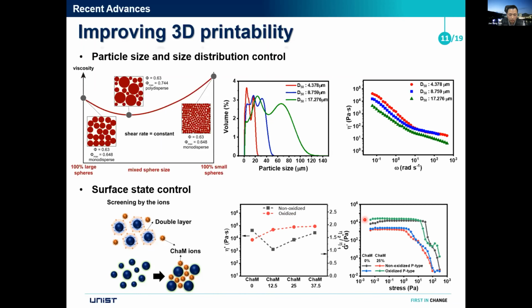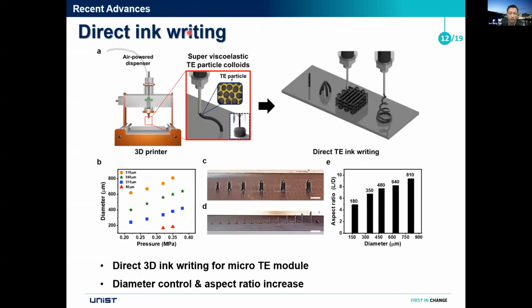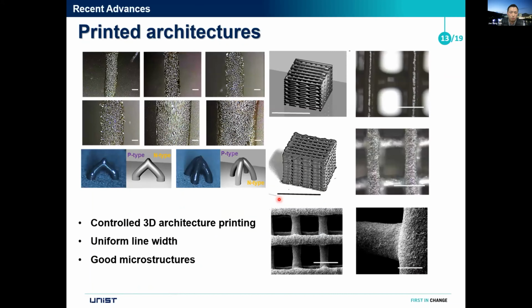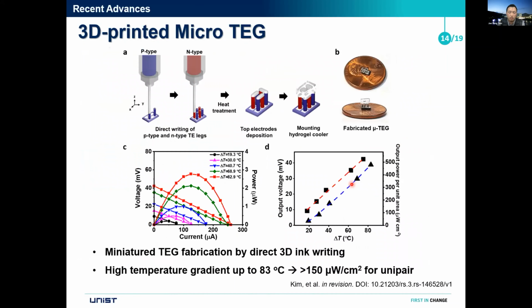By using these inks, we realized direct ink writing, or 3D ink writing, to produce thermoelectric filaments. The diameter of these filaments ranges from 100 micrometers to millimeter scale. And then we can design and fabricate some complicated architectures, P-type, N-type bridge structures, and some scaffold-like structures. And these thermoelectric layers have quite high ZT values, about 1.1 for P-type and 0.5 for N-type.